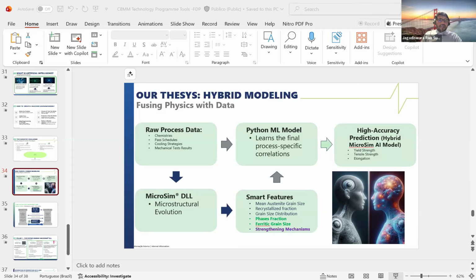To make this model, as I mentioned, the key important thing is that the physics engine is the microsim model, which is unpacking the metallurgical brain, which we call the microsim core. And module 2 is a phase transformation model, because these two models together will provide us most of the data from the rolling mills, which gives us the austenitic grain size, recrystallization fraction, strain accumulation, austenite grain size distribution, as well as the final phase fractions, final ferrite grain size fractions, and the dislocation density.